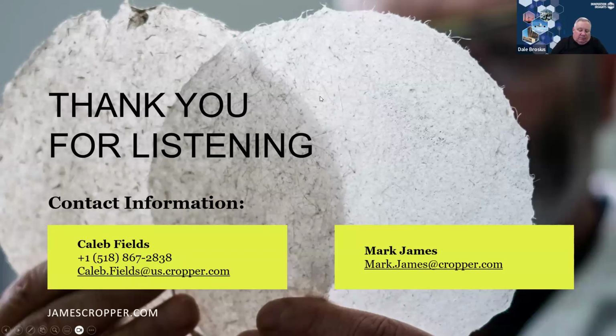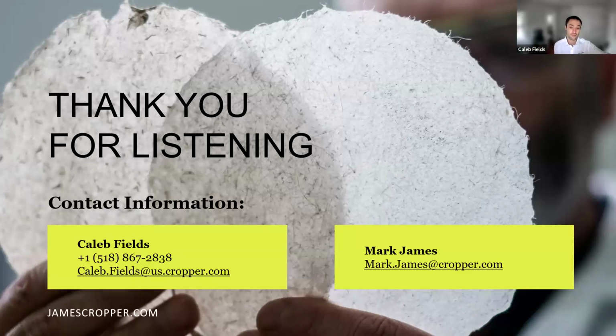Yeah, I saw some very lightweight solutions that you had there. What's the range of fiber areal weight that you typically have, from lightest to maybe even heaviest? Yeah, the lightest is 2 grams per meter squared. We can do that with a carbon, which is only about 3 carbon fibers thick. So it's very, very lightweight. Typically, customers are using in the 4 to about 75 GSM range, but we can go up to 200 and sometimes a bit higher depending on the application.